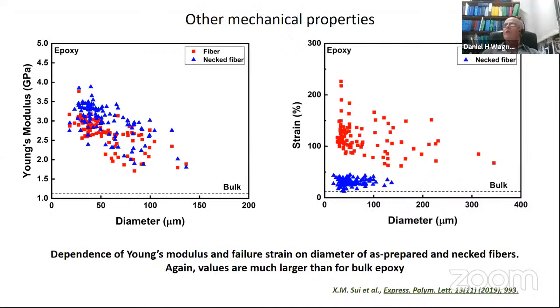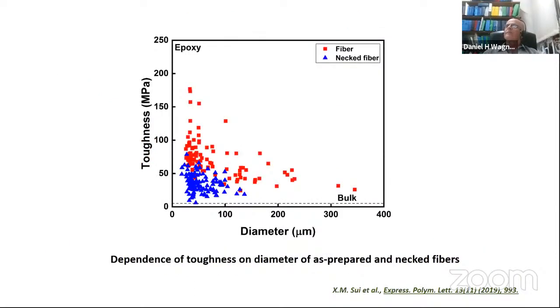And we have other properties that we've measured, and they also have a size effect. Young's modulus has a size effect, and it's way above the bulk value of epoxy Young's modulus. As you can see from below, it's 3 times or something like that on average. The strain is also much larger, but we know that because of the yielding. The yielding is totally unusual for epoxy, and this is what we see. So there is a huge difference between bulk epoxy as we know it and those necked fibers, or those thin fibers. Toughness, being simply the area under the stress-strain curve, also has a size effect. There's a dependence on diameter for both as-prepared and necked fibers. So we have all this data.